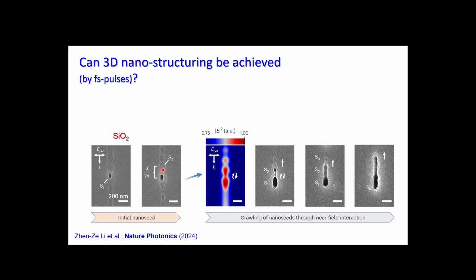Then we can also recognize that we have some different pattern, which is basically by interference, distance-separated from the original place. So it's obvious that modified regions are talking to each other, and this is how reflectivity is increasing, and then the energy of light scattered from those regions is interacting with the light which comes from the top. So this is propagation from the top downwards for this polarization. So we can actually imagine that just by waiting a little bit in time, pulse by pulse, we can evolve structures which are quite well localized, and they are getting longer, but not much wider.